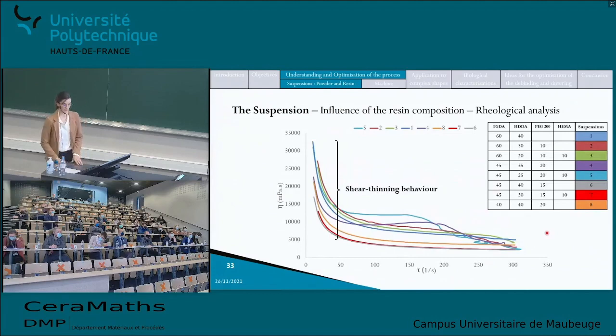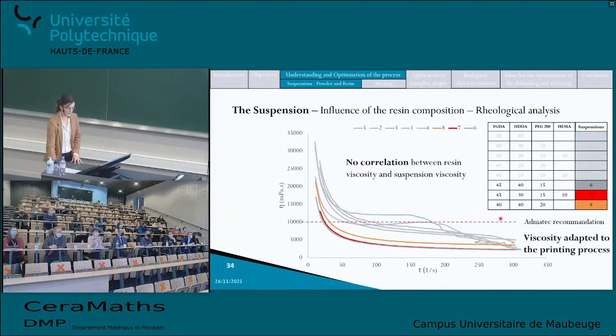However, Admatec recommends the use of viscosity below 10,000 millipascal second to be suitable for the use of the machine. So only 3 of the suspensions had a viscosity adapted to the printing process, even at the low shear rates. The suspension compositions 6, 7, and 8.